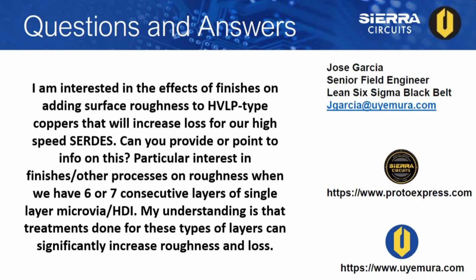On the very low profile, you can specify the bonding adhesion promoter, alternative oxide, that we put on. We control that. There's some new chemistries coming out that limit that buildup. The only thing with that is there are trade-offs on both the low profile dendrite structure and what they're using for the adhesion promoter, because the less you have, the more prone to delamination.